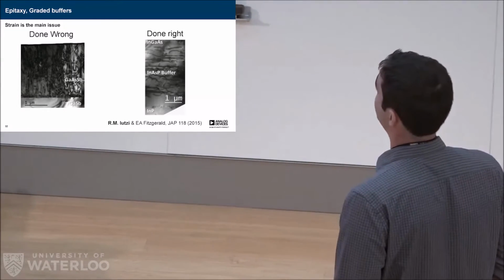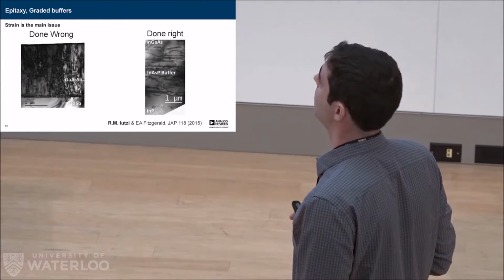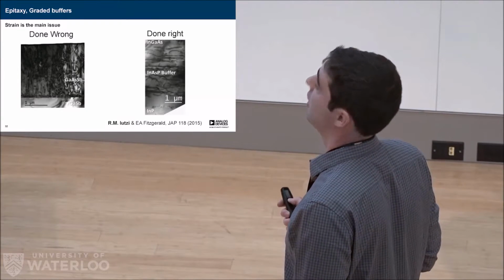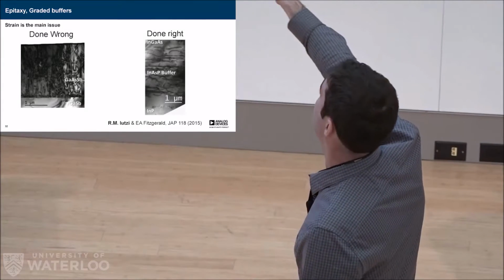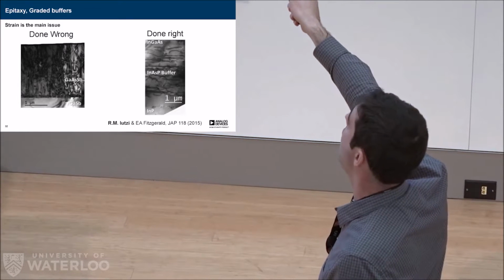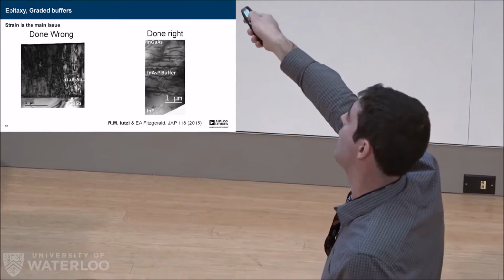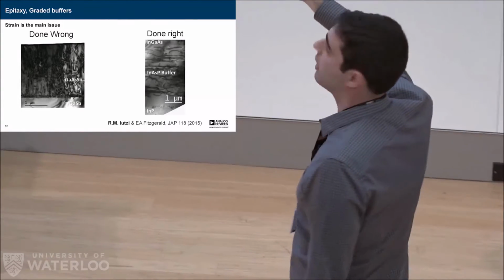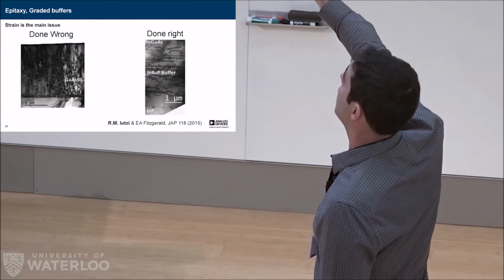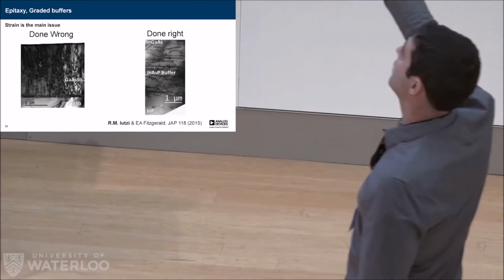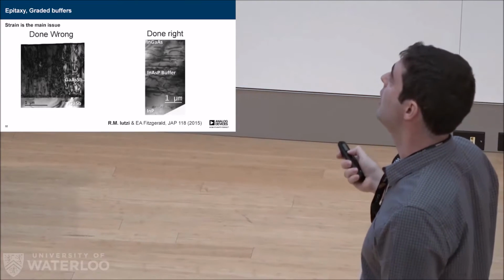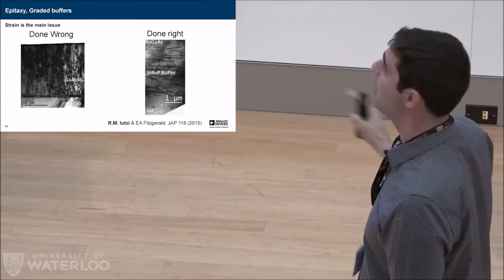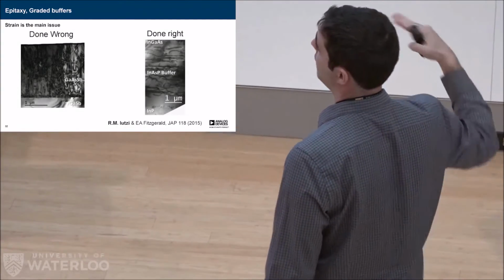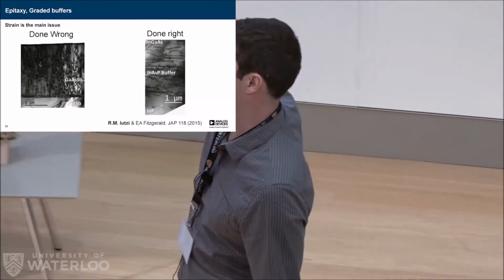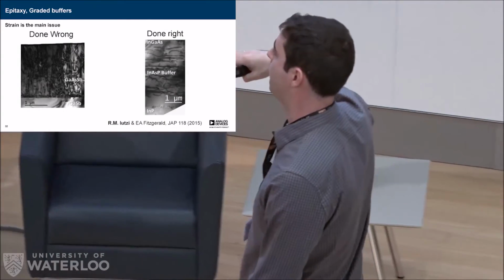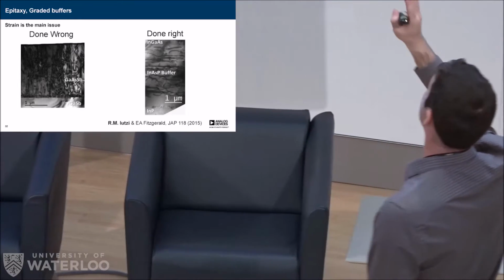You can play tricks though. In this particular one, I was trying to combine indium phosphide and indium gallium arsenide. So in a perfect world, I could have an indium gallium arsenide device up here, and then a small wire that goes down to an indium phosphide device down here. And I made it work by grading it very slowly with indium arsenide phosphide. So basically what I did was, I let it form these dislocations, but I made sure that it happened slowly enough that these dislocations just travel horizontally and relieve the strain. And then the few that exist go up to the surface, but not a lot of them do.